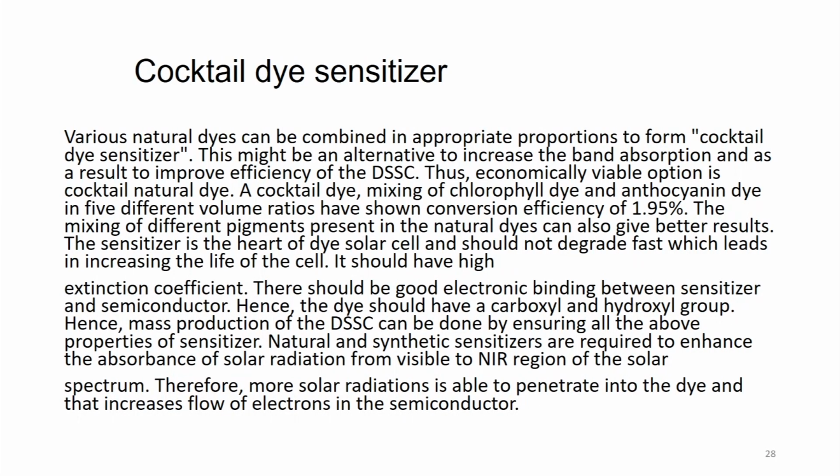A cocktail dye mixing chlorophyll dye and anthocyanin dye in 5 different volume ratios has shown conversion efficiencies going up by 1.95%. The mixing of different pigments present in the natural dyes can also give better results.